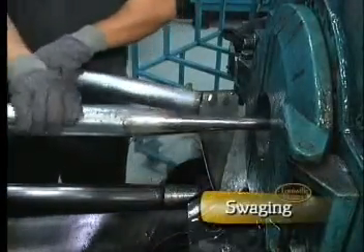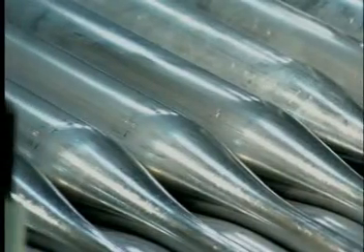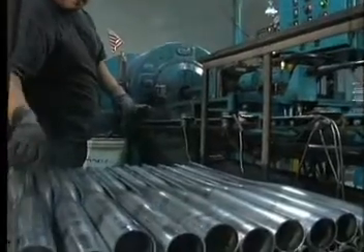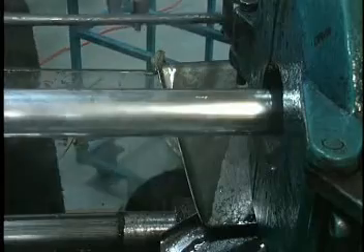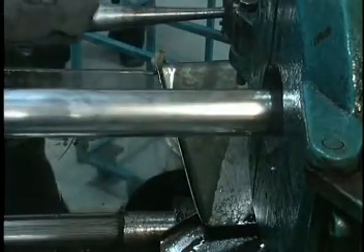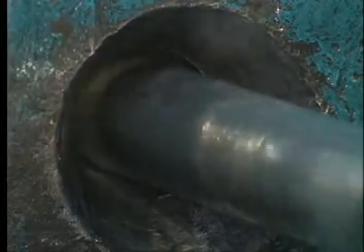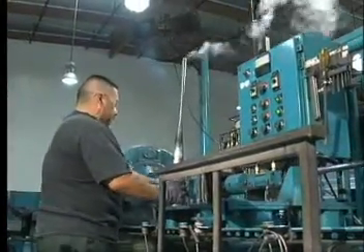The next step is swaging, or shaping the bat. Barrel and handle diameters vary between models. Where the bat begins to taper also differs depending on the model. In the swaging process, the shape of the desired bat model is machined into 2 opposing dies. These dies rotate around the tube as it enters the machine, while also moving in and out to impact the tube and reduce it down until the desired diameters are achieved. As the tube is tapered down, it grows in length.